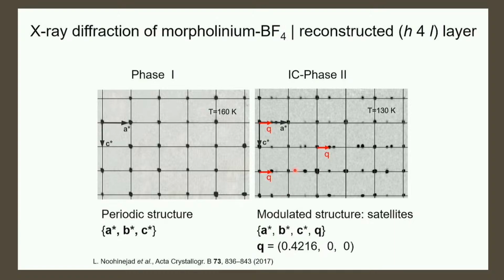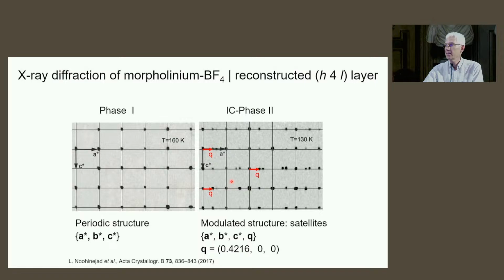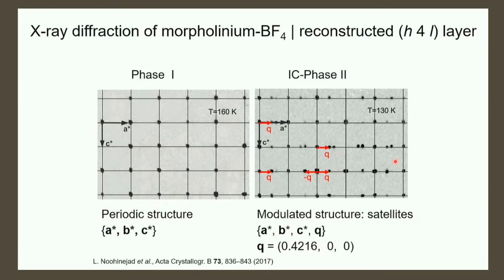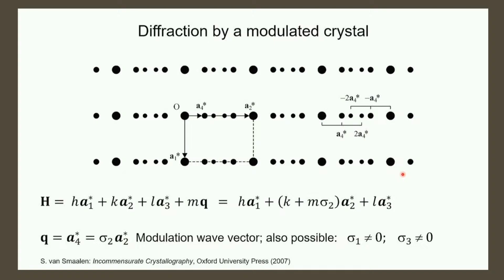Sometimes there is missing, that's allowed, or invisible intensity, or not measured intensity, but there are no other positions, and in particular, wherever you do it, you need the same q, which here is 0.4216 A star. Mathematically, we can also have minus q, which explains why we have 2 of these satellites close by. One is plus q from the left, and the other is minus q from the right. And this is schematically a similar idea, where we have A4 star or q, alternative ways to denote q, or A4 star is this irrational fraction times A2 star, as we had before. And here it's chosen in such a way that the first and third components of q are 0.